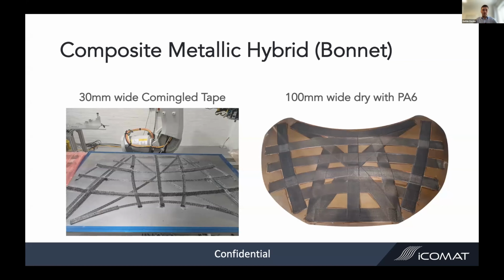So what are we looking at in the automotive industry? Well, it's all very well and good laying down one tape and putting a bit of a curvature on it, but what if we put multiple tapes down and put curvatures into them, so we can apply the tapes only where it's required? We were working with an automotive OEM to lay down the tapes for this bonnet on the left-hand side of the screen. So this is where the load path is on a bonnet, and using a 30mm wide commingled tape, we created this structure to essentially reduce the amount of materials you need to make that bonnet by not having an inner panel, not needing the assembly operations for applying the two sides together. We are able to reduce the amount of work needed to make that bonnet quite significantly.